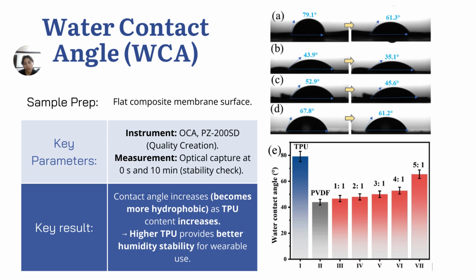The water contact angle of the samples was measured using an optical contact angle device, and tensile properties were evaluated using standardized specimens tested at room temperature. As the TPU content increased, the water contact angle also rose, indicating lower surface energy and weaker van der Waals interaction at the surface. This change improves the humidity stability of the temperature sensor.